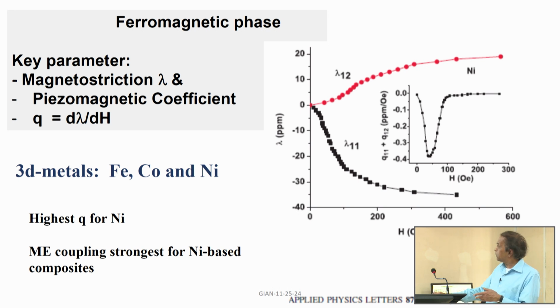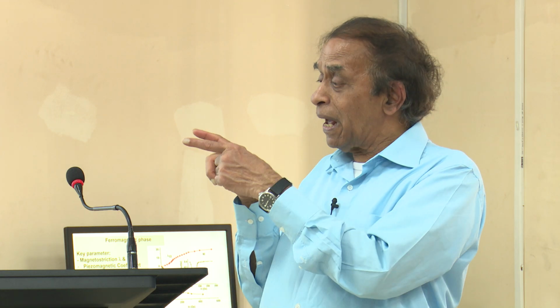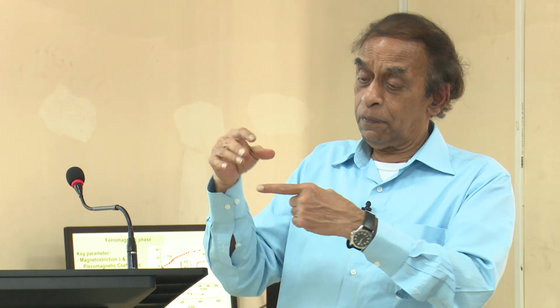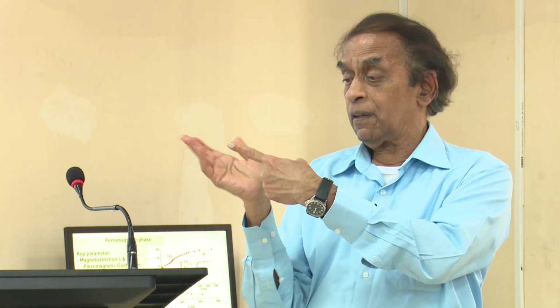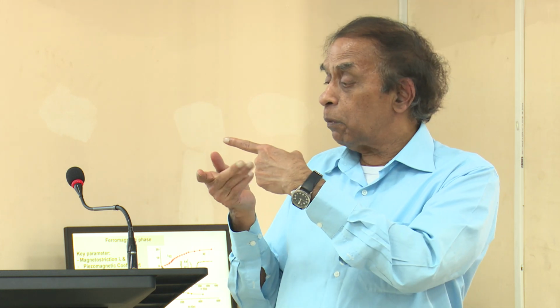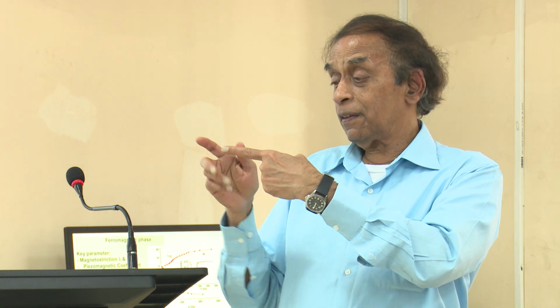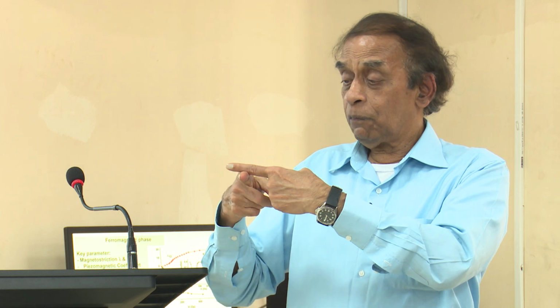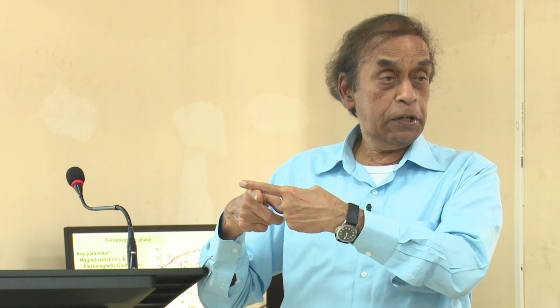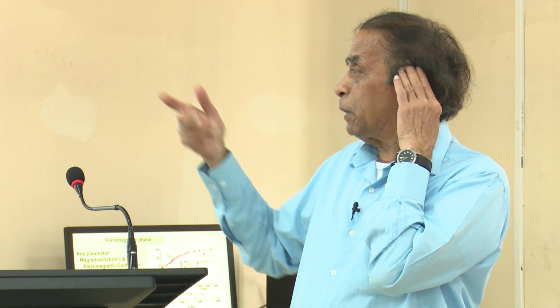So, when we measure the magnetostriction, we use a strain gauge. For lambda 11, if this is the sample, the strain gauge is attached to the surface, then you apply a magnetic field parallel to the strain gauge. For lambda 12, the strain gauge is oriented this way, the field is applied perpendicular to it. That is how lambda 12 is measured.